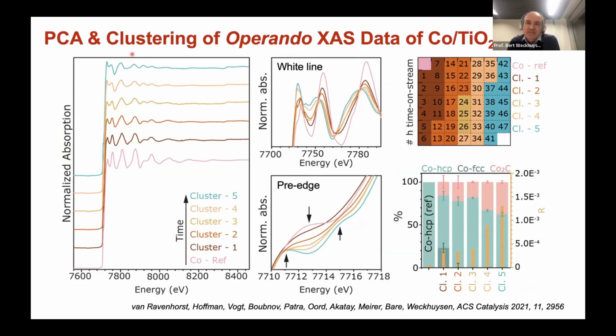We clustered them, and we found 5 typical clusters next to the reference. And here I show you that you first have the first component, then the second, then the third. And here I show you the differences in the pre-edge and the white line for these different clusters. What are now these clusters?